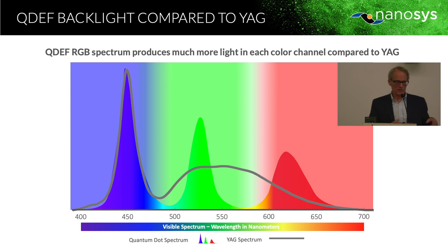So here, if we look at this spectrum, I'll show a typical white LED. It's basically a blue LED with a YAG phosphor that creates that broad hump. And so if you're trying to make blue, red, and green light using these color filters, you see that the red light is kind of weak and its majority is very much near the green edge of the color filter. The green is very broad. And if you compare that, and what you would do then is get rid of the YAG phosphor and just use a blue LED and add quantum dots, now you see that there's much better color purity in this implementation than there is with just a YAG phosphor, for instance.